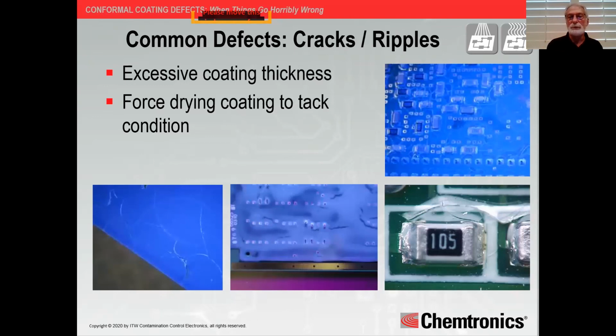Cracks and ripples. These are actually some very good pictures. If you have excessive coating thickness, if your wet film is way too thick, and especially if it's a high solids content coating, it doesn't cure evenly. It doesn't allow that solvent to evaporate evenly, and especially at the surfaces. And then you get strains and stresses in that coating, and it cracks.